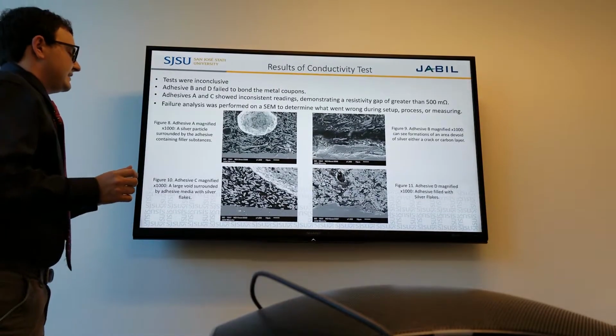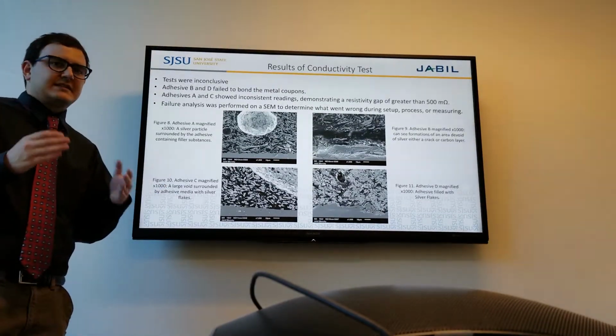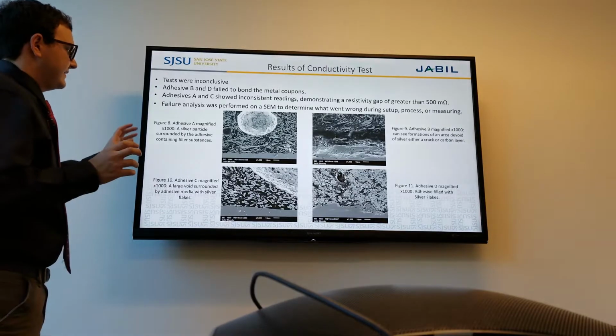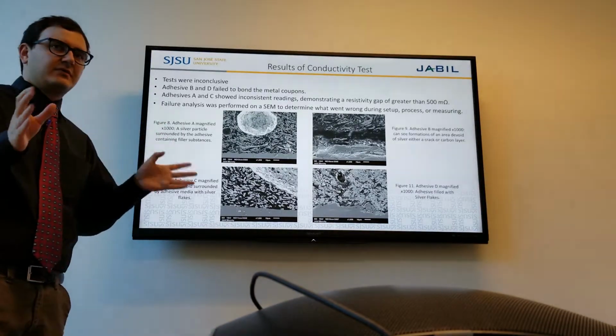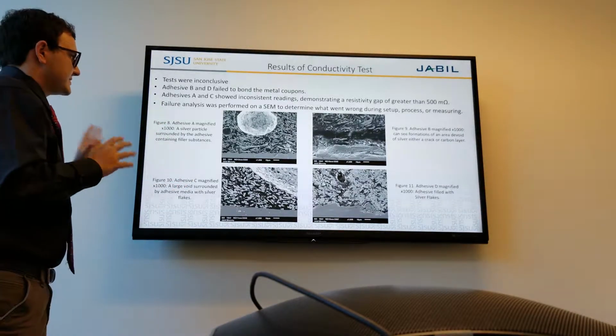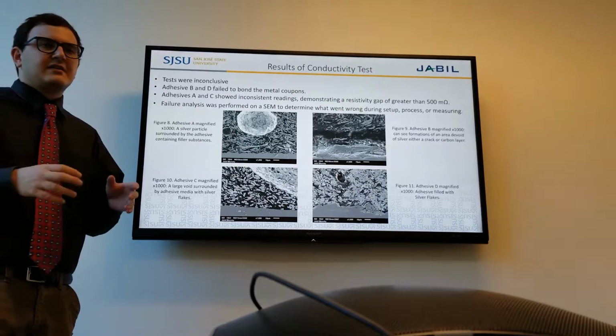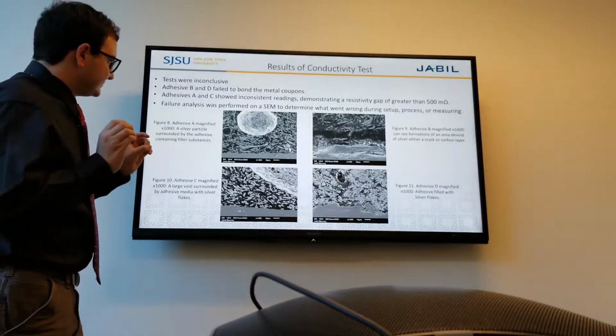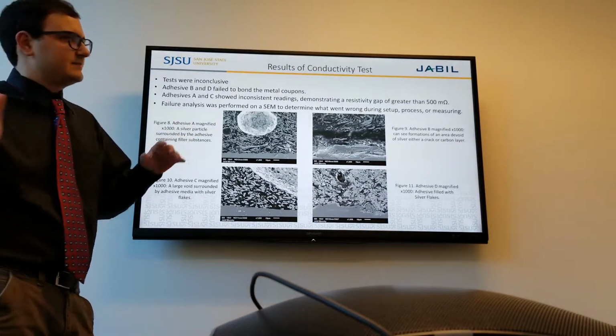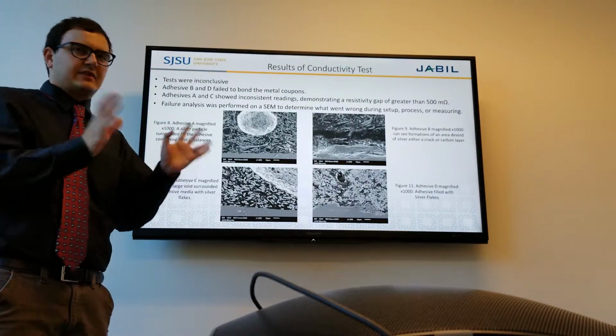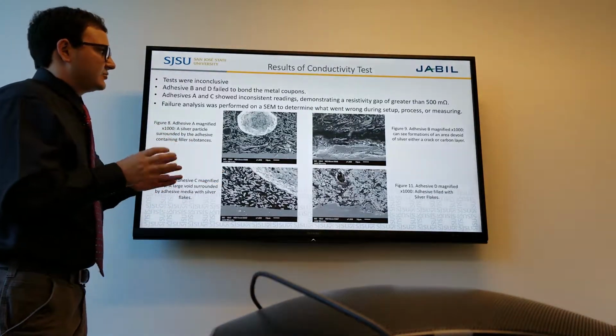For adhesive A, where conductivity was a problem and consistency was a problem, we found that there was an uneven distribution of silver particles. The more silver particles in the adhesive, the more conductive it would be. But in certain coupons, there were not as many silver particles as the more conductive ones. So something in the future will have to be done to control that.